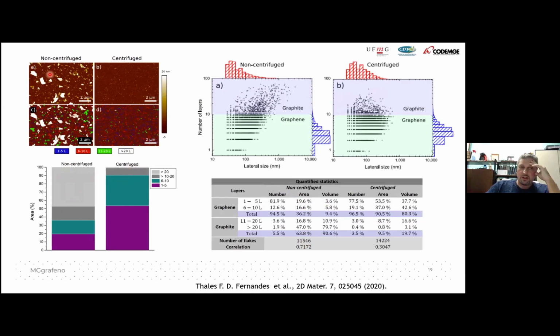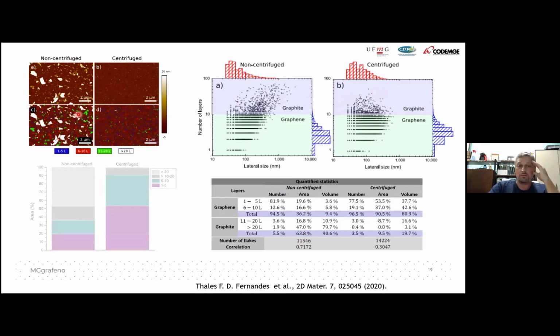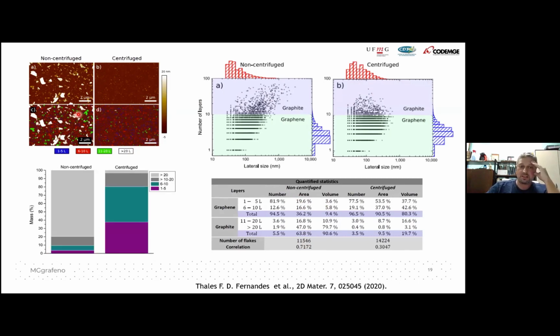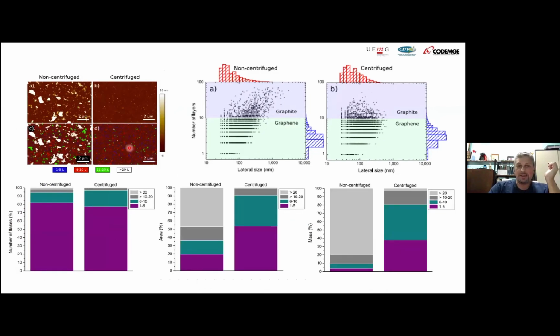So, okay, area is something that really translates what we are seeing here. This is the real statistics that shows what we are seeing here. But there's another dimension which we are not seeing from this image, which is the volume. If we take the volume statistics, which is really what you are buying, if you buy this sample here, you are buying 90% graphite. If you buy this sample, you are buying 20% graphite in terms of mass. So they look very much the same, depending on the numbers that you show.